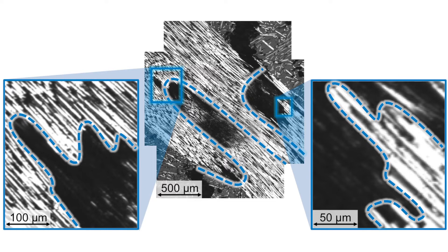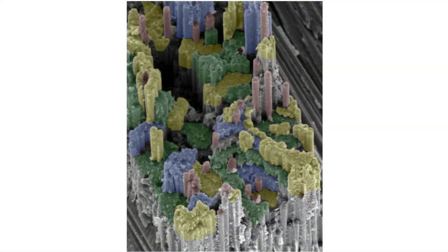Back in 2008, we started being interested in analysing the failure of fibre bundles in a composite. One thing we noticed was that the failure surface was self-similar across a wide range of scales. We then looked back at translaminar fractured surfaces in cross-ply laminates and noticed that there too, there were several scales in the fractured surface.